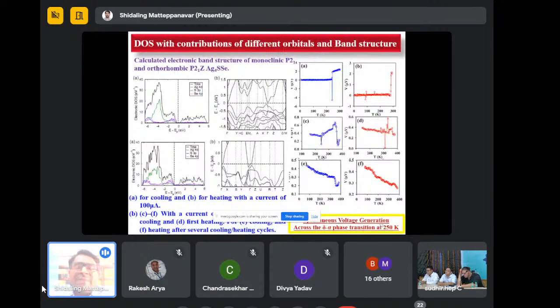And then we have done the band structure calculation for both structures, the monoclinic structure and the orthorhombic structure. The band structure calculations well support our experimental results. Here we can see that there is an overlapping of the bands when it goes to the orthorhombic structure. We have also measured the spontaneous voltage generation in this sample. Around the transition, it is producing this spontaneous voltage generation.